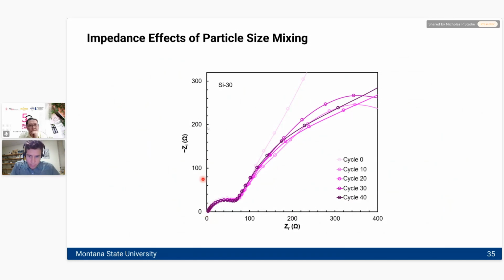This is a Nyquist plot, and we see two semicircular features in the electrochemical impedance spectra of this very nice mixture, Si30. They show pretty good stability over those first 40 cycles, which is what we like to see. Cycle 0 is obviously different because you have to set up a lot of solid electrolyte interphase in that first cycle. But this relative stability of the electrode over the first 40 cycles was very promising for us as compared to any other silicon that we'd ever looked at.